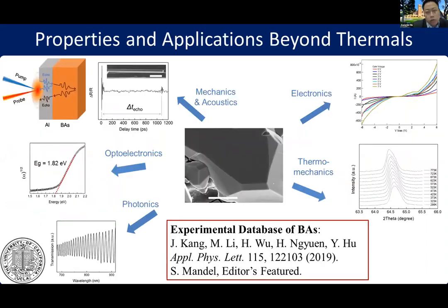So in addition to thermal properties, as a newly discovered semiconductor, many other properties have not been explored. So we recently developed this experimental database of boron arsenide, measuring multi-physics properties, including mechanical and acoustic properties, elastic modulus, hardness, the band gap of 1.82 eV, optical refractive index, thermal expansion, and also electronic properties. We hope this study can serve as a starting point to inspire more research in many different areas for this new semiconductor.